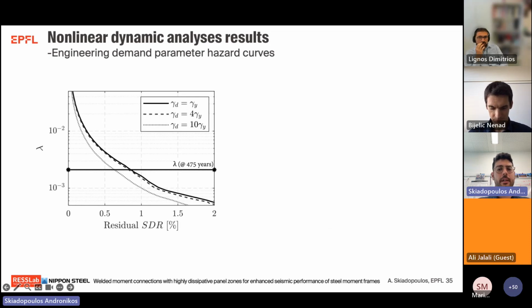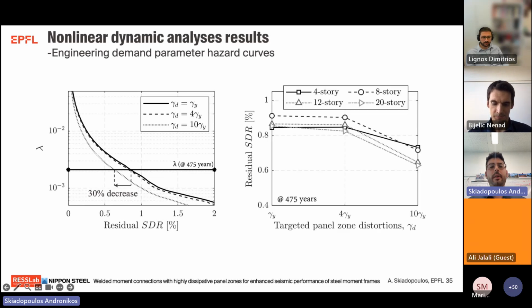Finally, engineering demand parameter hazard curves are developed, as shown on the left figure. On the vertical axis, we see the mean annual frequency of exceeding the targeted engineering demand parameter, where in this case the engineering demand parameter is the residual story drift ratio of the moment resisting frame at the end of the dynamic earthquake loading. What we see characteristically for the design basis event is that the residual story drift ratio decreases by up to 30% once we allow for inelastic deformations within the panel zone. On the right side of this slide, we see that the same tendency exists for all 32 archetype steel buildings that we designed. This is particularly important from a building demolition standpoint, which is controlled by the residual story drift ratios.